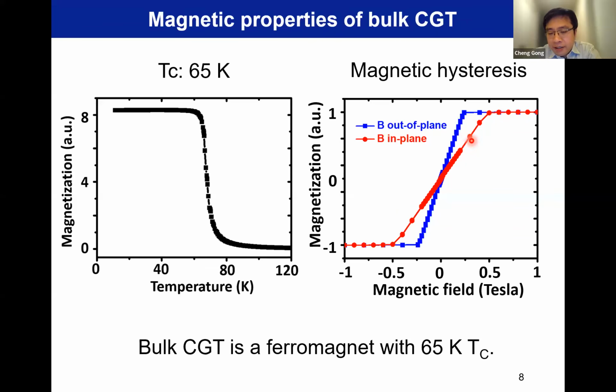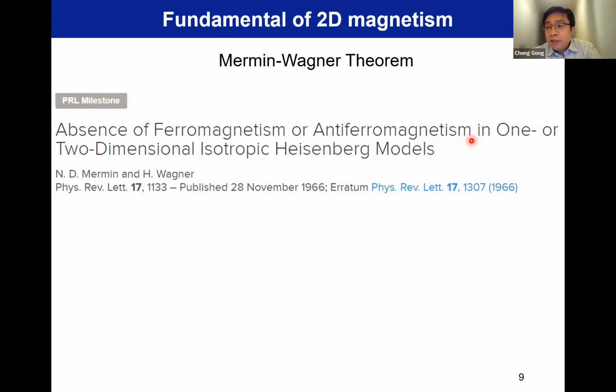I emphasize this because this is really important. In such a system, a 2D magnet, if you don't have an easy axis anisotropy, you will not break the continuous rotational symmetry. Without such continuous symmetry breaking, any finite temperature can easily excite those spin disturbances and destroy your order. This is the classic Mermin-Wagner theorem. As you can see, there is a condition for the isotropic Heisenberg model: you will never see finite temperature long-range magnetic order in a 1D or 2D system. But if you have an easy axis anisotropy, you can have it.